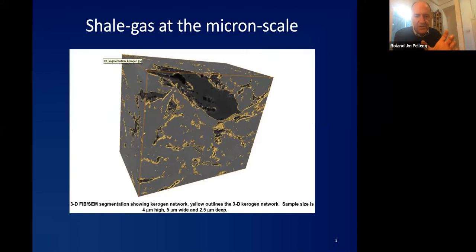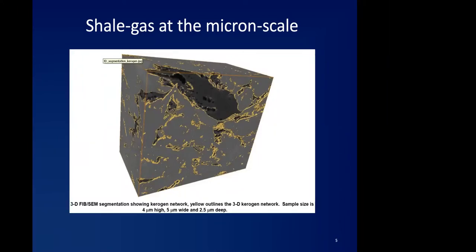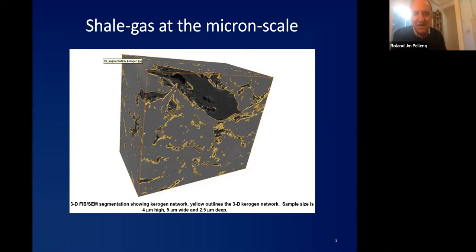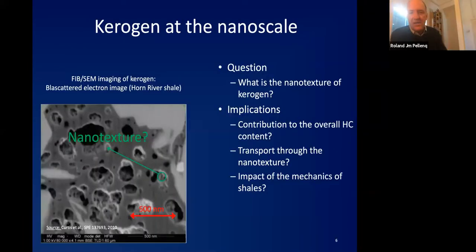So the box is actually a few microns, and you can see in yellow, I kind of picture the interface between those carbons, between the pores in the carbon. You see clearly that there is a big crack at the scale almost crossing the box, but we have some smaller pores, and actually even smaller pores. And I will show you that when it's in the gray, this is already also porous, but at the scale of nano.